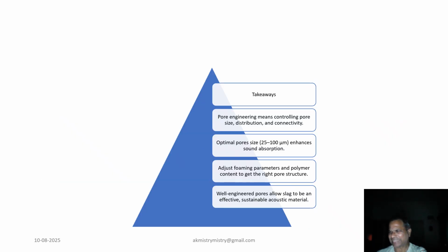Simple takeaways, we can say that to summarize, pore engineering means designing the size, distribution, and connection between pores. The best pore size for sound damping is about 25 to 100 micrometers. We can control pore characteristics using foaming methods, process settings, and material composition. With well-designed pores, slag becomes an effective, eco-friendly material for sound absorption.